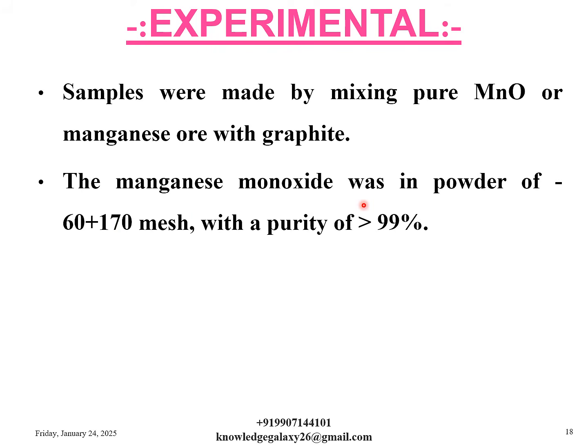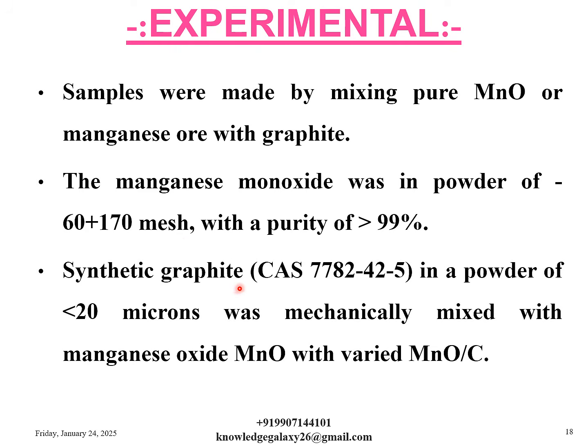The manganese monoxide was in powder of -60 plus 170 mesh with a purity of more than 99%. Synthetic graphite, CAS 7782-42-5, in a powder of less than 20 microns was mechanically mixed with manganese oxide MnO with varied MnO by C ratio.